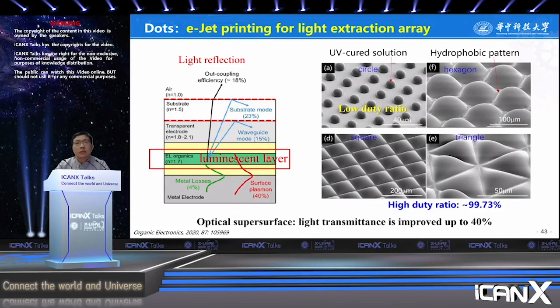EHD printing can generate high viscosity UV-curable solution, and high aspect ratio dots can be obtained. However, the duty ratio is very low, like this one. The anti-reflection effect is limited. One of the most important tasks is to increase the duty ratio. A hydrophobic pattern is adopted to form the fine mesh. The pattern is fabricated by the EHD direct writing process that we'll discuss on the next page.